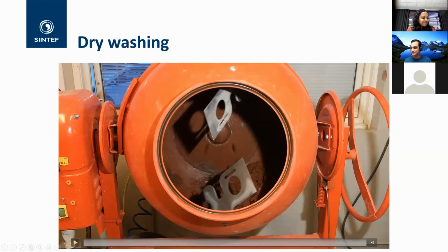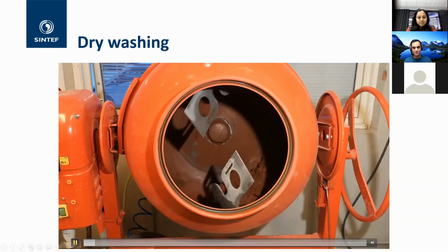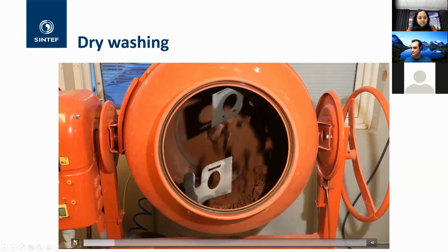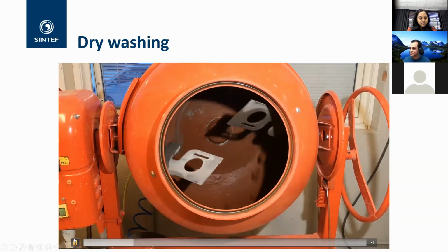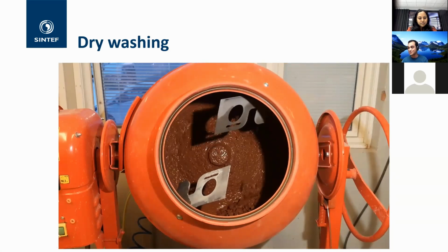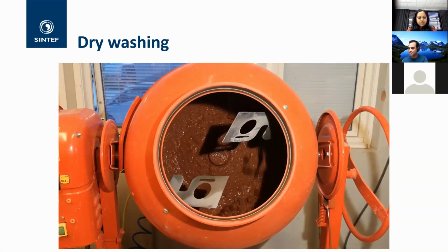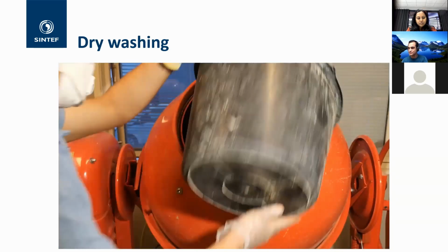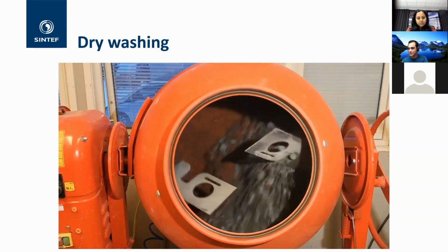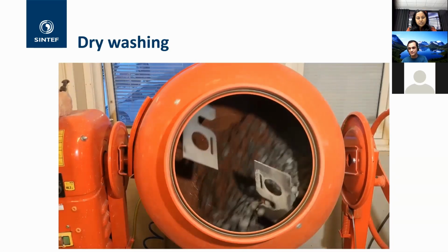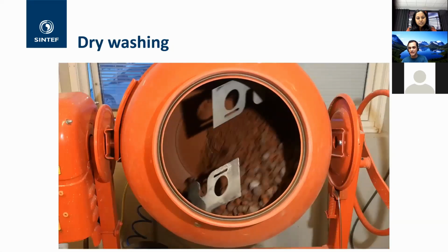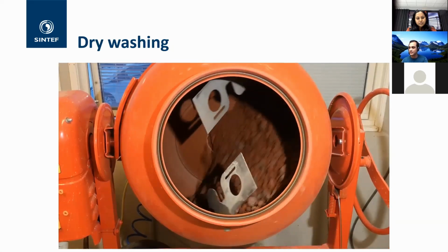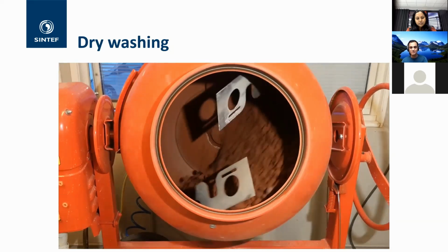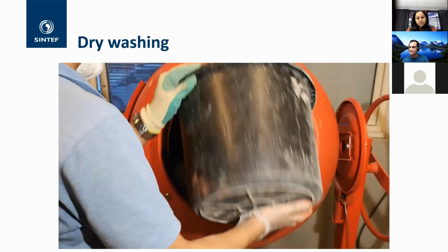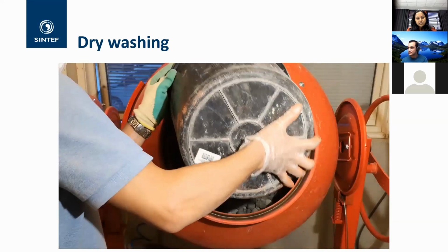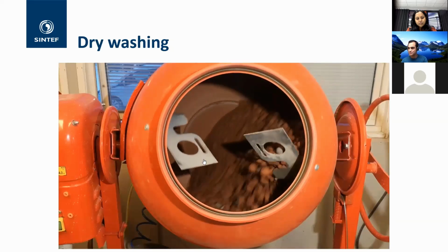Sorry, before moving further, I will present a video of a dry washing process. So here in the concrete mixer, we mix a small amount of concrete, simulating some return concrete on the concrete truck. Then we added the Recon-Zero aggregates from the previous cycle, and we mixed it for a few minutes. And after some time, the aggregates that we added bound with all the concrete in the drum. The red color is because of the pigment that we added to distinguish between different layers. But the concrete drum is quite clean.